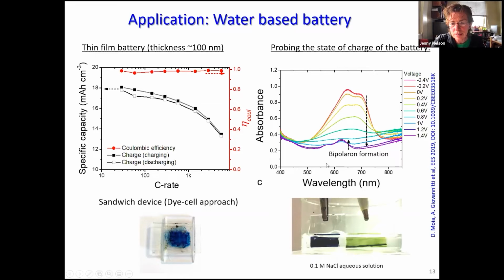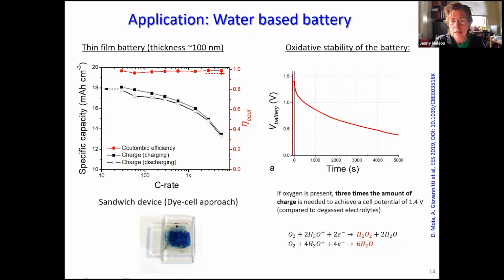We see the characteristic color changes in the battery, showing us that the bipolaron is formed in both materials. We also measured the stability of the device, and we find, perhaps not too surprisingly, that in the presence of oxygen there is a loss in capacity, and that means that you need more charge to achieve a given cell potential if you work in the presence of oxygen.